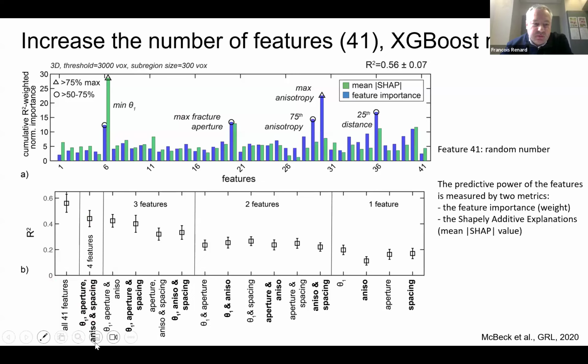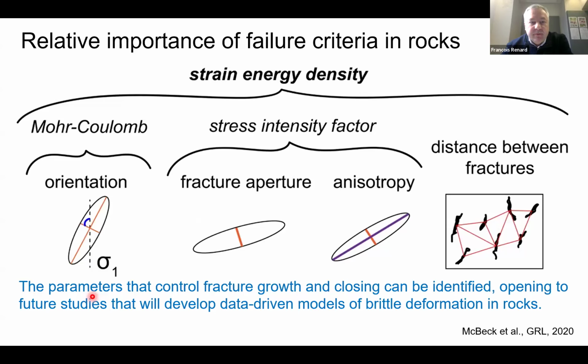But if we look at these 4 parameters, the orientation of the fracture, the aperture, the spacing, what it says is that the orientation of the fracture is part of the Mohr-Coulomb criterion on how a fracture will propagate until the system will fail. The fracture aperture and the anisotropy, so the ratio between these 2 axes, that's under the stress intensity factor, so that's fracture mechanics. And the distance between fractures, so how fractures interact, that's a measurement of how the strain energy is distributed in the volume.